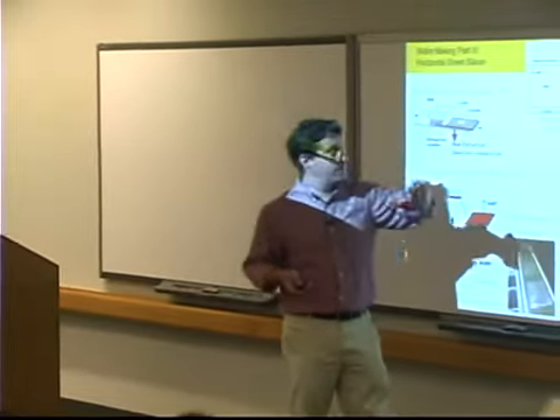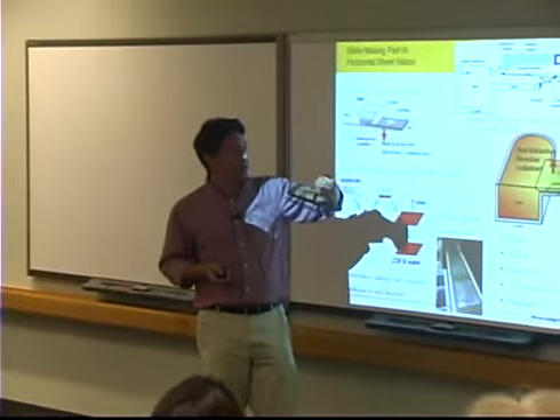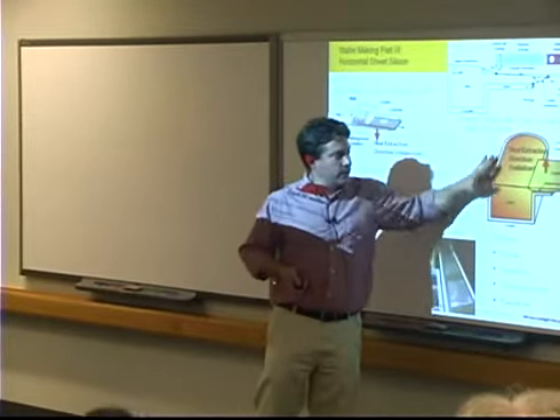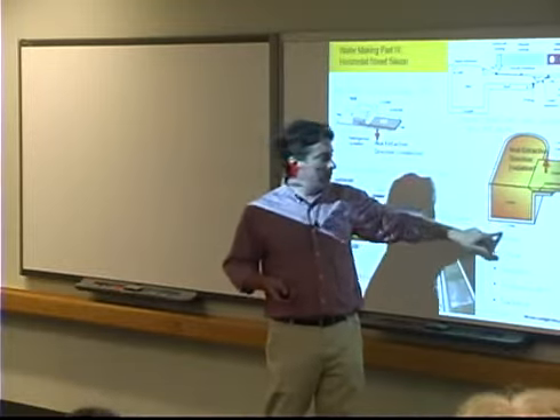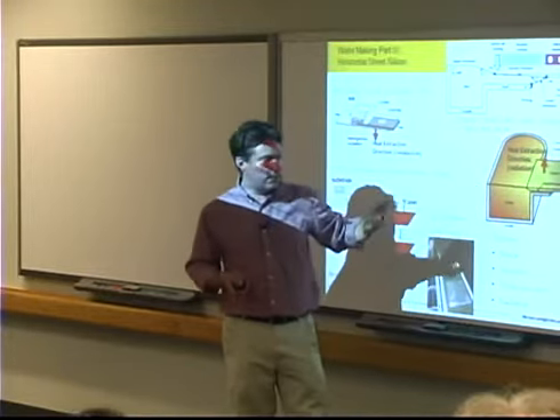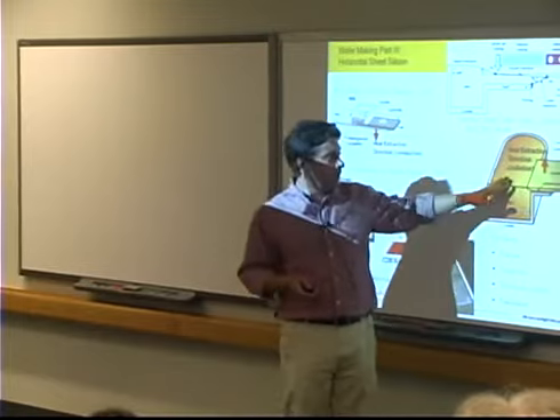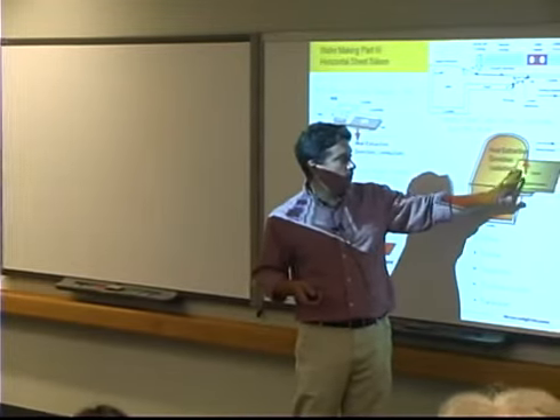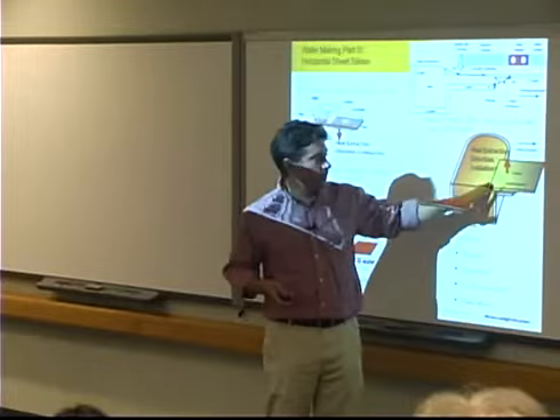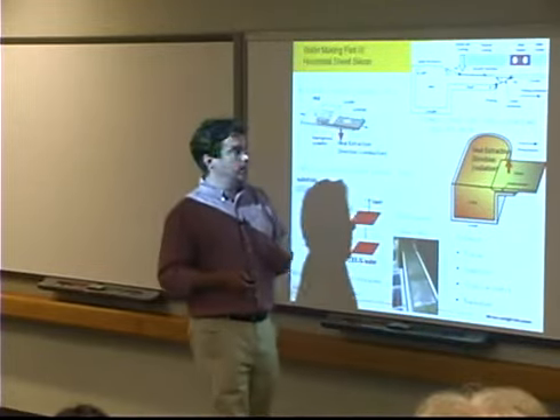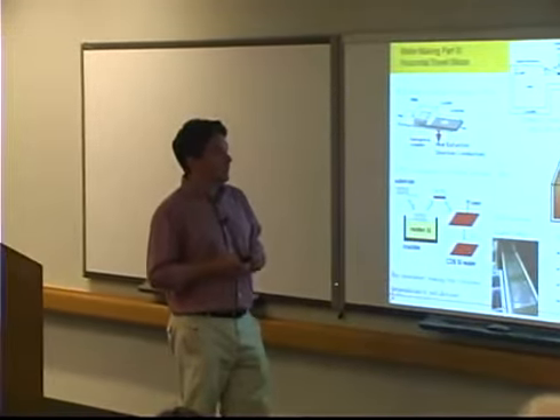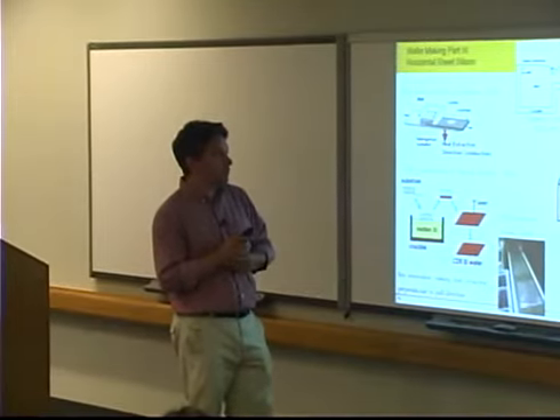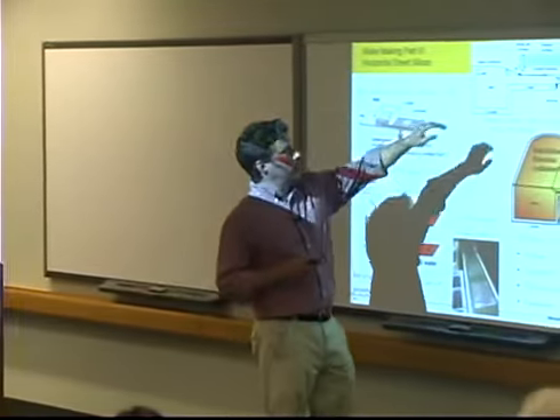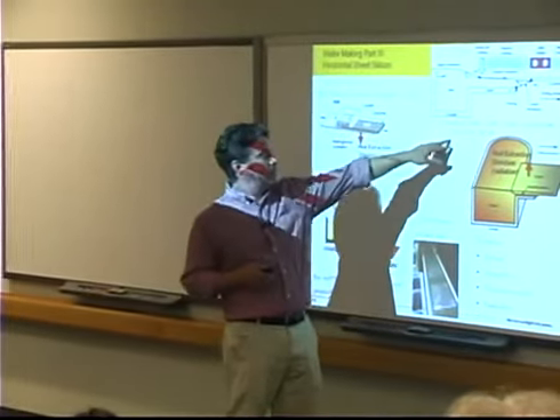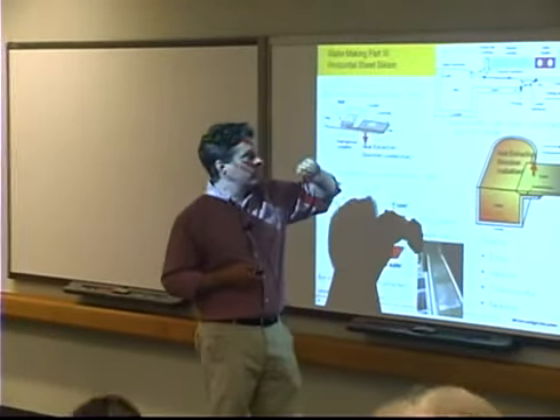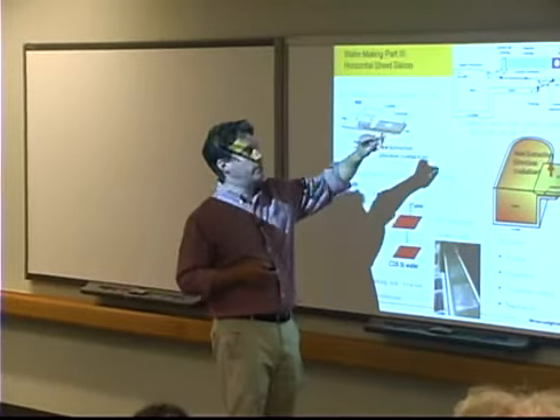This one is, I think, maybe the most interesting. Here you have this bowl of liquid silicon, and again there is a container here that is going to have some kind of impurities associated with it, but what you try to do is crystallize this sheet of silicon off the edge of it, and in the ideal case this should be a single crystal as well. A paper was actually published just very recently in the Journal of Crystal Growth looking at this from a theoretical point of view.